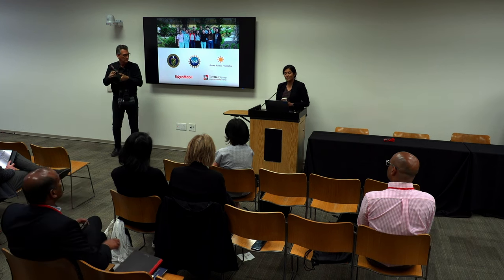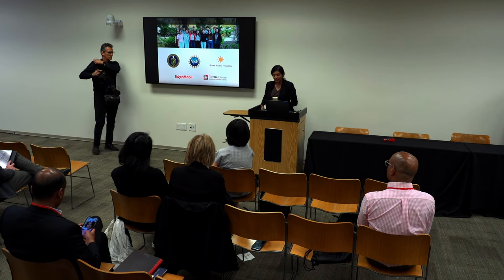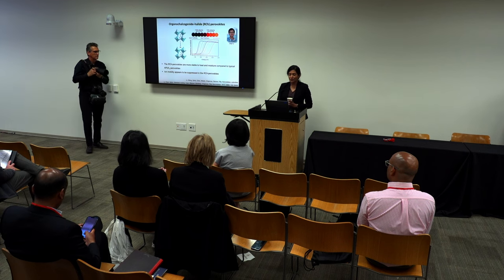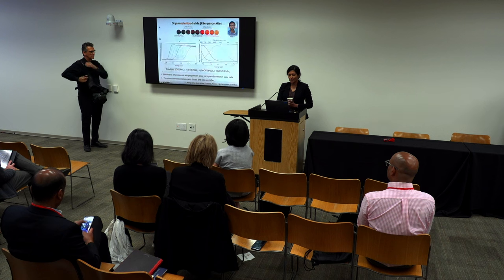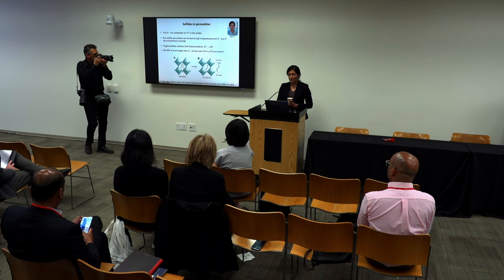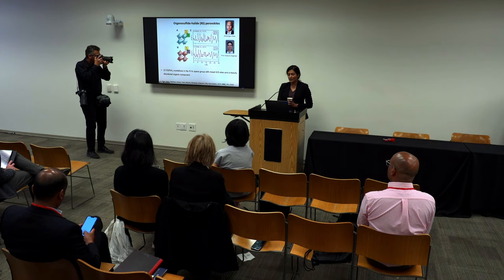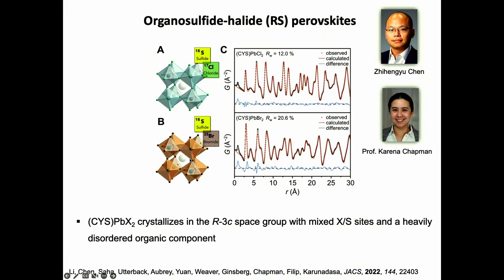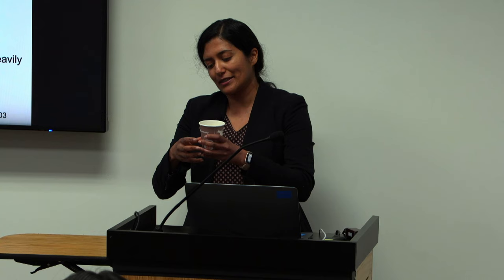That's a great question. Yeah, so it's random. So here I'm showing you one configuration, but if you look at the actual crystal structure, I don't show you the organic part at all because it's perfectly randomly situated, so it's perfectly disordered. And that is why we think we have this large octahedral tilting. So another thing we really want to do is reduce the size of that, or perhaps make the cavity larger using the inorganic framework to try and reduce that tilting.